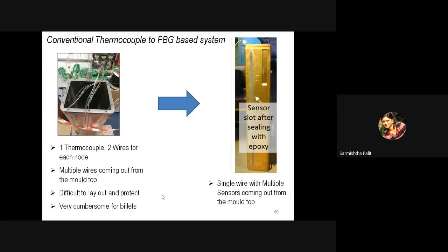Now here, as I told, the thermocouple is ruled out. Think of a billet mold which is cylindrical in shape, a copper mold, as you can see on the right side. It goes inside a jacket, and surrounding that high pressure water is sprinkling. In that, you cannot make a hole. Suppose you want to embed thermocouples: how many would you use in a 1 meter length mold? If you look at the left side, it will look like a patient with a large number of tubes in his body, and all these tubes have to come out from the mold plate. So this is completely ruled out. Thermocouples cannot be used. Till date, for any billet mold, there is no way of measuring the temperature of the mold face, and whatever decision is made is based on the mathematical model.